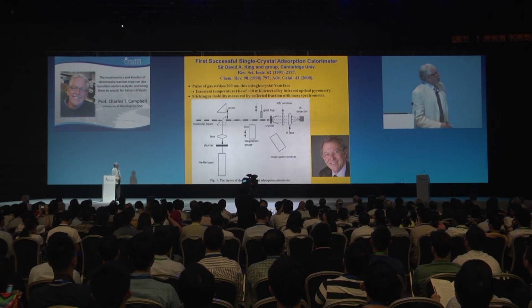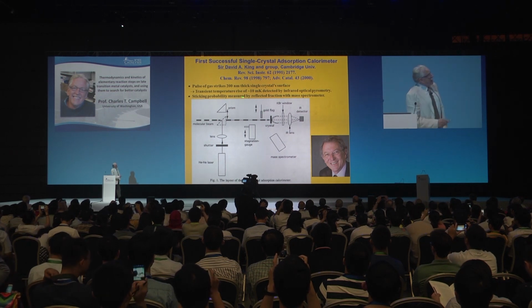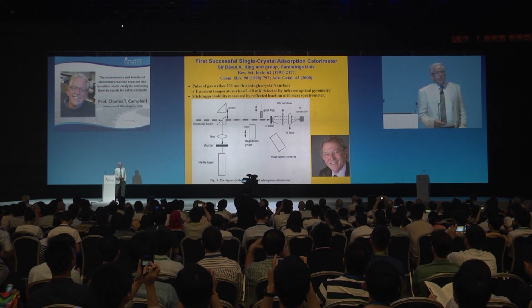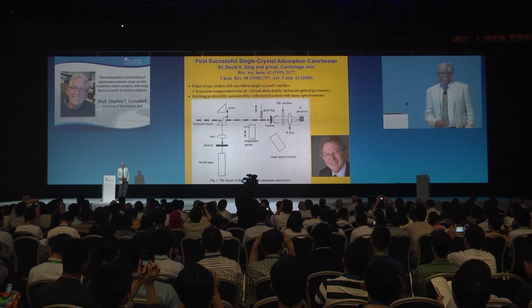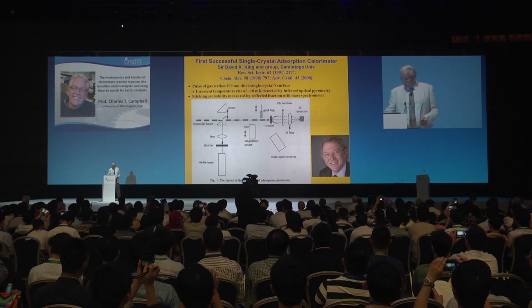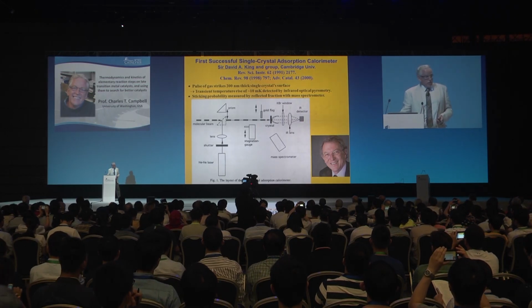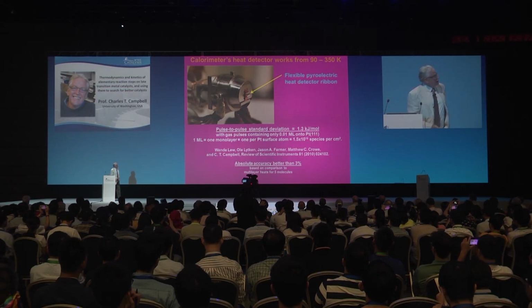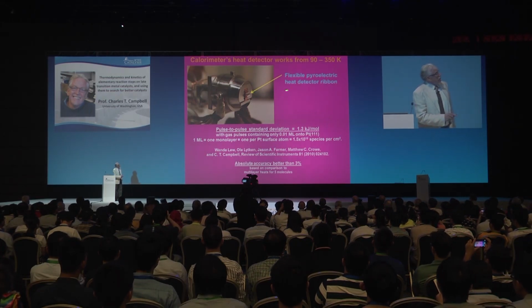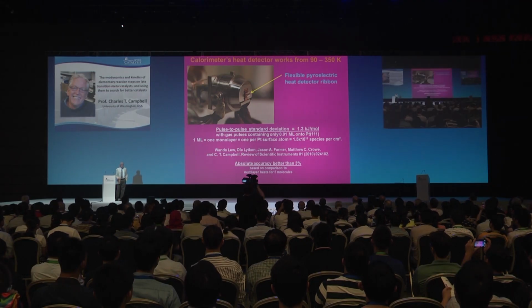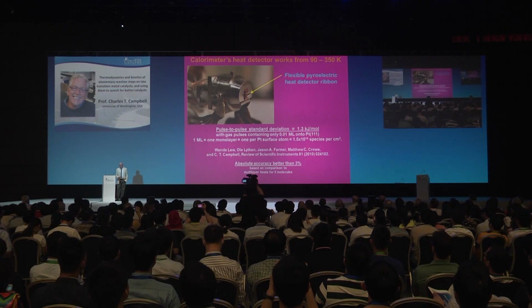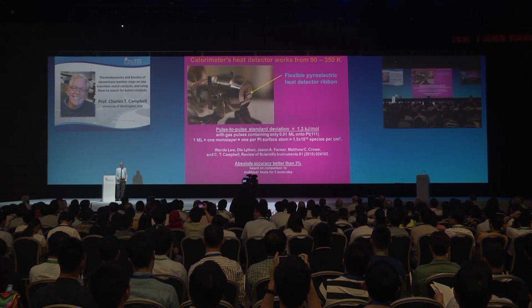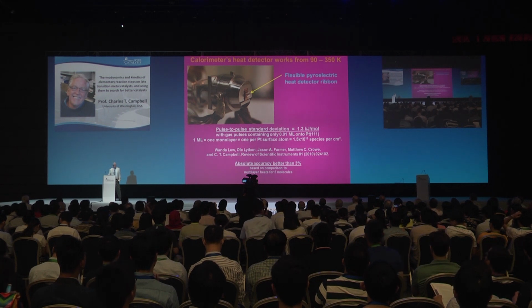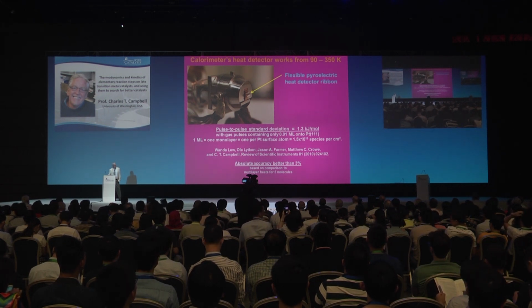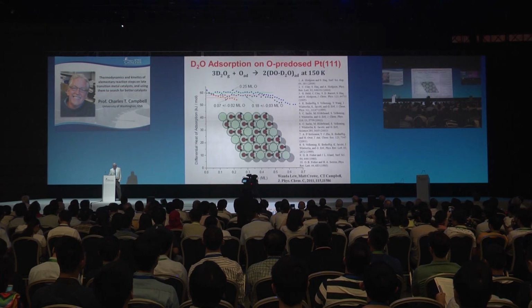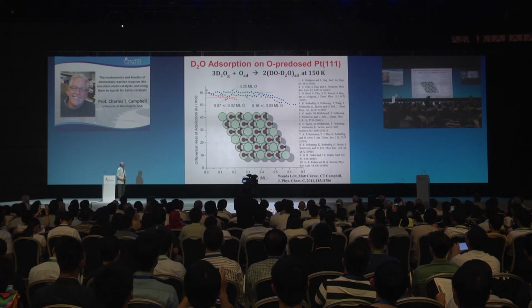Dave King, now Sir Dave King, recognized this early on, and he built a calorimeter that could actually measure the heats of adsorption of things that were irreversibly adsorbed on surfaces. It was the first time that kind of measurement could be made on a single crystal surface, and we followed his techniques. I won't talk much about it, but we invented a new heat detector that's about 400 times more sensitive than his heat detection method at 300 Kelvin. At liquid nitrogen temperature, it's about 10,000 times more sensitive, so you can do a lot of experiments that he wouldn't even be able to attempt with his heat detector. And so I'm going to talk for a little bit about the energetics that we measured.